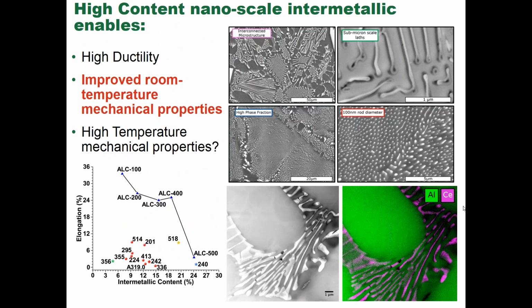Here we see some of the original microstructures that were done, and you should be able to see the various scale bars on there. What we have is a very, very small aluminum-cerium phase. When looked on edge, the rods are about 100 nanometers in diameter. When you add cerium in percentages of between 8 and 10%, you have a very, very high phase fraction of cerium in the material. The microstructure is interconnected.